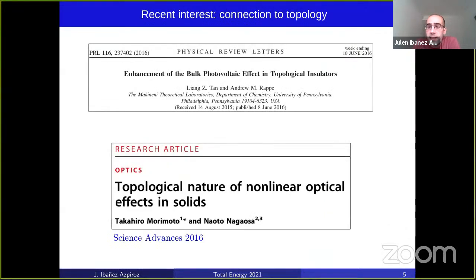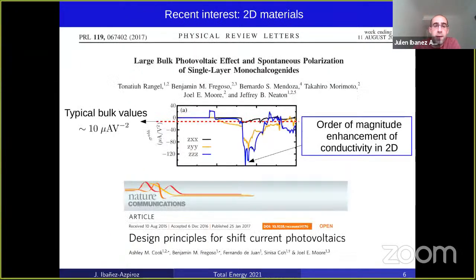Now, the recent interest is motivated because the bulk photovoltaic effect and more generally nonlinear optical effects seem to be closely related to some fundamental properties of materials like topology. For instance, the work in the upper panel, a density functional theory work, showed that the shift current experiences a sudden change of sign when the topological phase boundary is crossed. So it's very sensitive to the topology of the system.